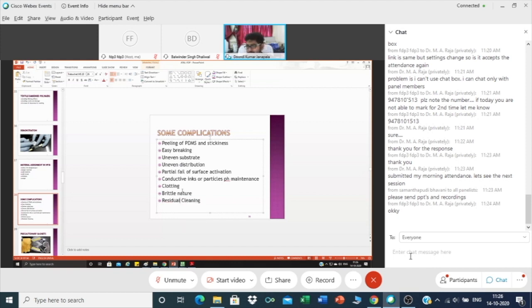Residual cleaning. After you do all this process, the toughest part of this research is cleaning your vessels. Probably leave the vessels for a few days and the residue will get hardened. When the polymer residue is hardened, it is easy to clean. If there is any residue, I prefer acetone to clean it, then it will become very good. Each time before you start, clean your vessels with acetone and use a hair dryer to dry them, and then you start the procedure.